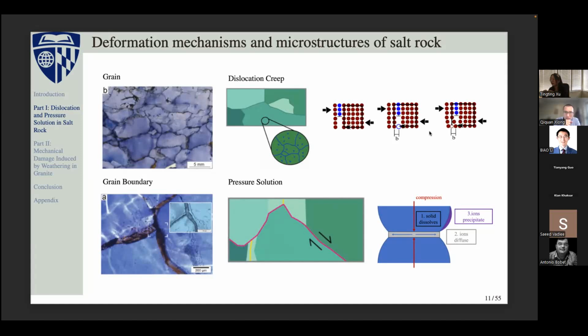The pressure solution is a chemical reaction, and from the sketch at the right bottom, you can see that under compression, there are two grains in contact with each other, and the solid will dissolve under this compression force, and then the ions will diffuse along this contact boundary. And the third step is that the ions will precipitate on the low stress or stress-free surface. So those are the two deformation mechanisms that we really want to consider in this study. And all of these mechanisms are time dependent.